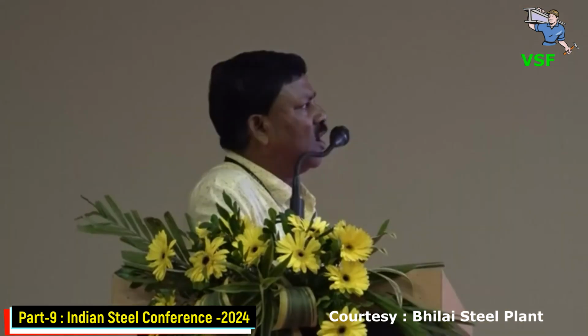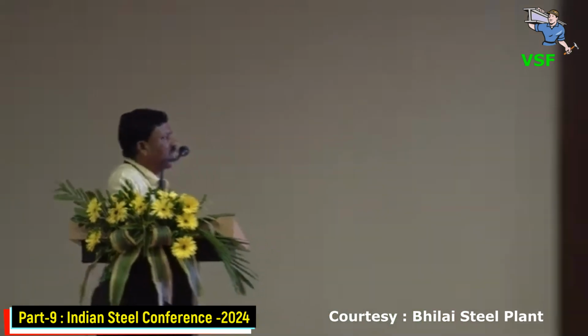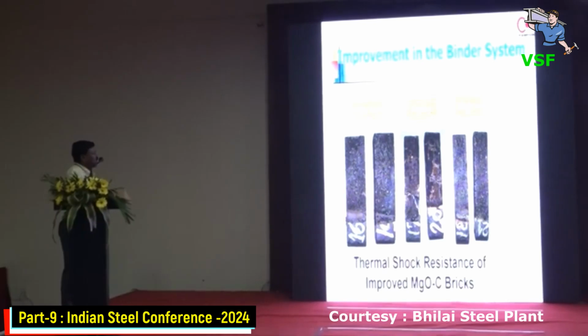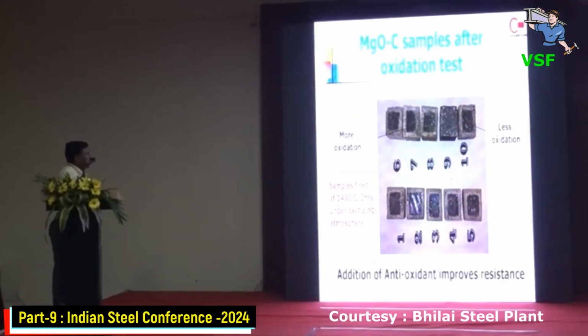This is the thermal shock resistance, a dynamic test where you put the magnesia carbon brick into an induction furnace, and then you can find out the different types of cracks and their thickness. This is about the thermal shock resistance test. You can see the binder plays an important role. Binder 1 is giving a lot of cracks, binder 2 is not much cracking, but we are using a combination of binder 1 and 2.